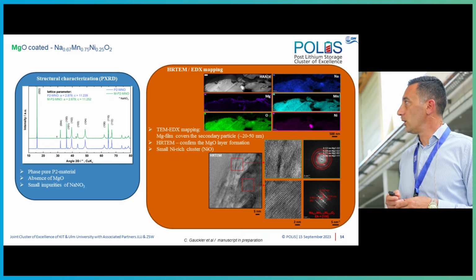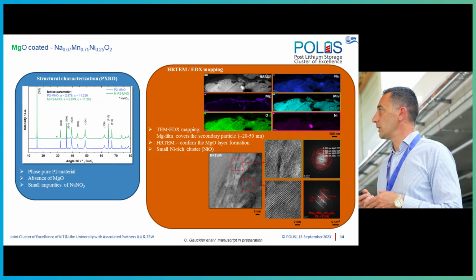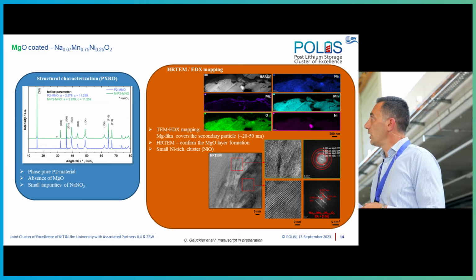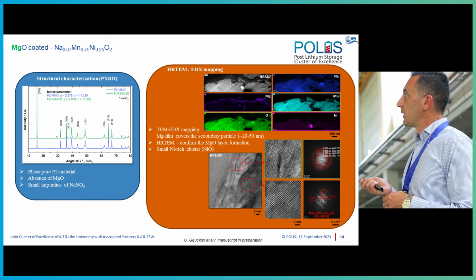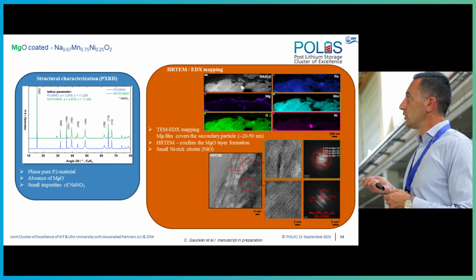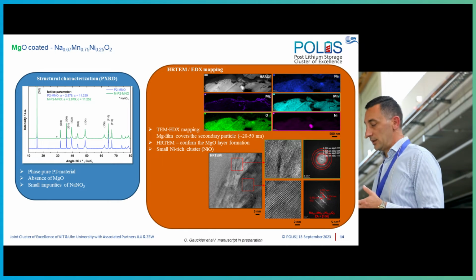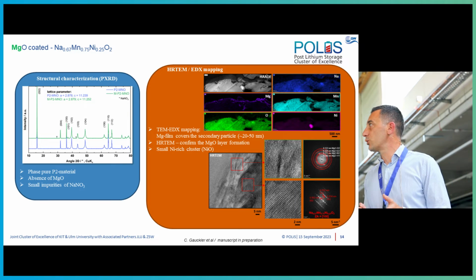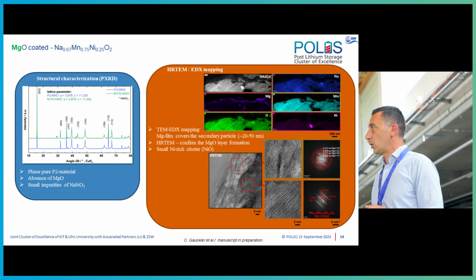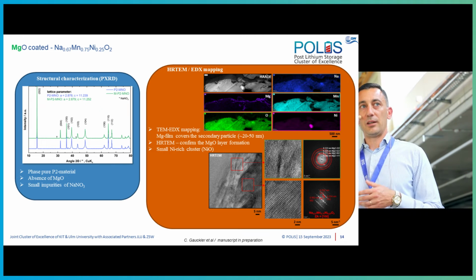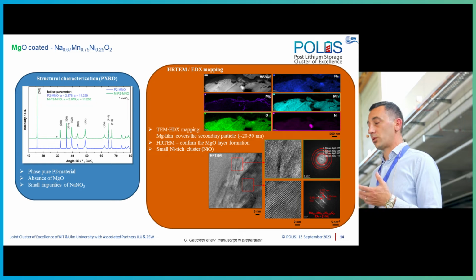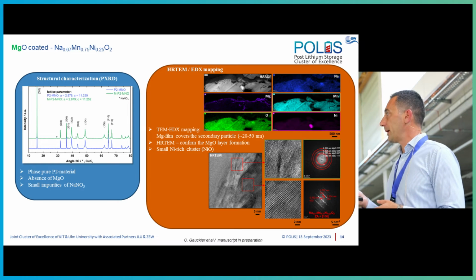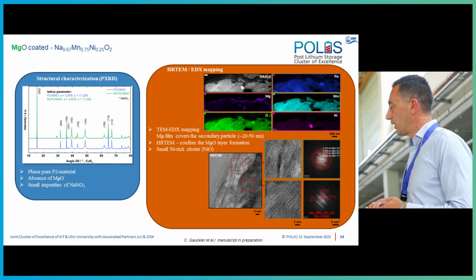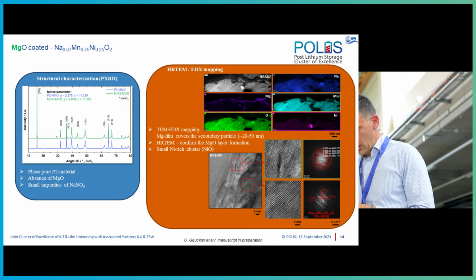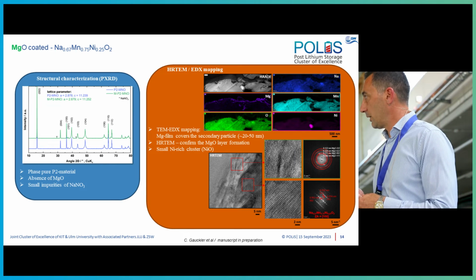And then we looked at the TEM and high-resolution TEM with the EDX mapping. So now, if you look at this picture, you basically can see, I hope that you can see, a magnesium layer just on top of the particle. And this is in the range of 20 to 50 nanometers in thickness. Now, we couldn't actually see any magnesium oxide from the powder X-ray diffraction data. But doing the selected area electron diffraction, then we could actually prove that magnesium oxide is there.